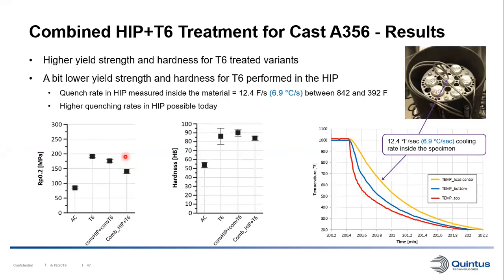And the reason for this is that the cooling rate in this HIP we used for this trial will be a little bit slower than water quenching. So we can see the cooling rates that we achieved in these specimens for that HIP cycle. However, this study was performed 5 years ago, and since then we have developed our furnaces even further. So today we can achieve significantly higher cooling rates than this. So I believe if we would redo these trials, we would get this strength up a little bit.